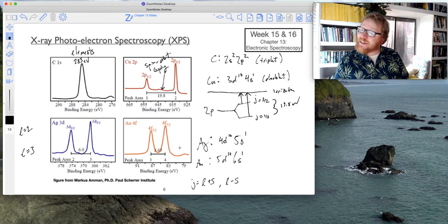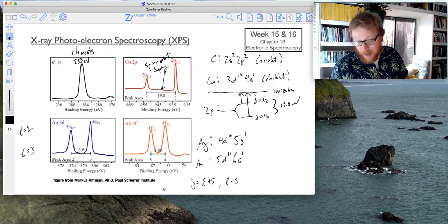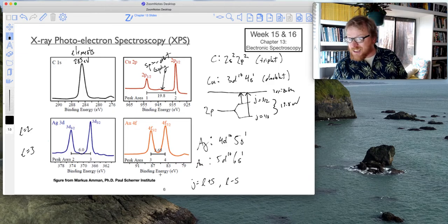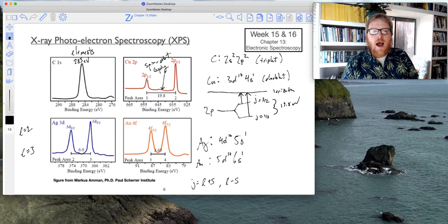All the same, what's important about this spin orbit splitting constant is it is a constant, and it can be used as a diagnostic tool to identify what you have in your sample. So suppose you're analyzing a sample and you don't know what its composition is, right? So when you get doublet peaks like this in this orientation, that will tell you, okay, I'm looking at a doublet state. And then when you calculate from the peak to peak, so that's all the spin orbit coupling constant is just the difference between the peak to peak.